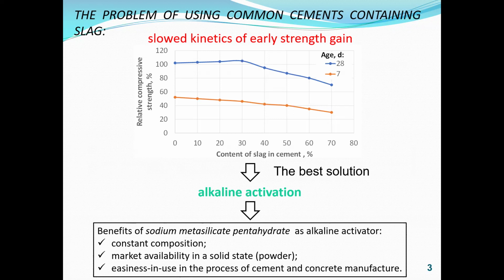Sodium silicates, the anions of which are similar to hydrated initial products of destruction of the alumina-silica-oxygen framework and serve as their additional reserve, are found to be the most effective alkaline activators. The best solution is the use of sodium metasilicate pentahydrate due to its constant composition, market availability in a solid state, and easiness in use in the process of cement and concrete manufacturing.